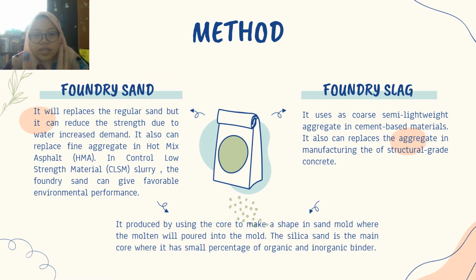Next is foundry byproduct, which has two materials, which are sand and slag. Actually, it is produced by using the core to make a shape in a sand mold, where the molten metal will be poured into the mold. The silica sand is the main core, with a small percentage of organic and inorganic binder. So foundry sand will replace the regular sand, but it can reduce the strength due to the increased water demand. It can also replace the fine aggregate in hot mix asphalt, or HMA. In controlled low strength material CLSM slurry, the foundry sand can give favorable environmental performance.